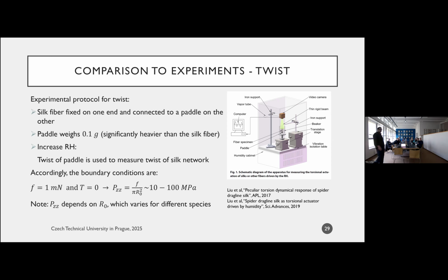But it does force us to think about the boundary conditions of this problem, right? Because now we have a fiber, the fiber is under a dead load, and we are increasing relative humidity. And so the force is roughly 1 millinewton. The torque is about 0. There's no torque that's being applied. And the nominal stress, or the dead weight stress if you want, is something along the range of 10 to 100 megapascals. It really depends on the radius, and different fibers have different radii, right? So it could be 3 micrometers or it could be 7 micrometers. It could be 10, right?